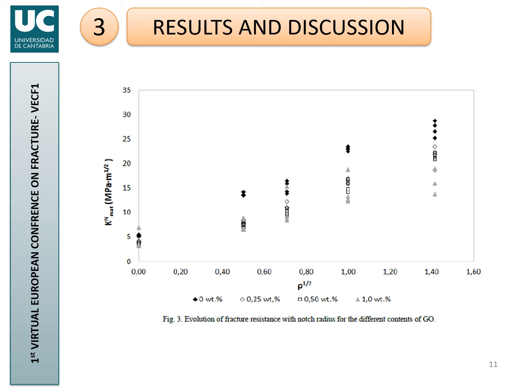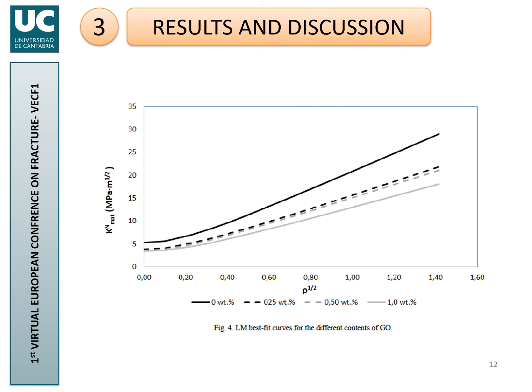The evolution of the apparent fracture toughness is shown in the figure, where it is clear that the higher is the graphene oxide content, the lower is the result in terms of apparent fracture toughness. We have adjusted these curves by using the line method expression just to have a much clearer picture of what we are seeing. Here you have the results. I mean, the effect of the graphene oxide is clear.